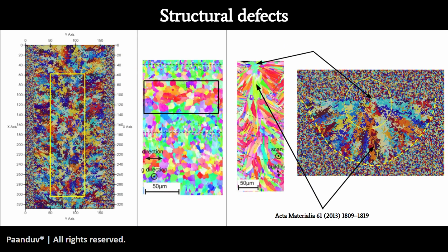Moving on to the microstructure defects, or I'm calling them structural defects, because microstructure data can give you very good pointers towards how well this particular build part is going to behave when it comes to the mechanical properties, the mechanical strength of the build. You can see a lot of equiaxed grains formed, and a lot of columnar grains are formed towards the edges, towards the solidification face of the melt pool. However, as we move right towards the center, you can see the circle here, more equiaxed grains are formed.